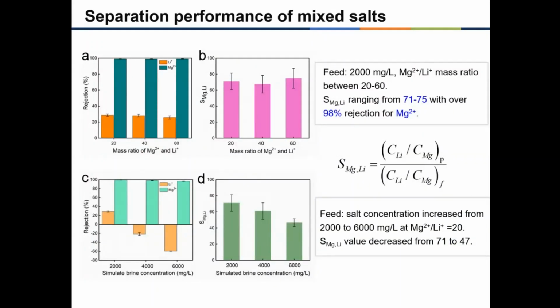We further tested the mixed salt of magnesium chloride and lithium chloride with total ion concentration of 2000 ppm, with the mass ratio of magnesium-lithium between 20 to 60. We found a high separation factor ranging from 71 to 75. The separation performance of the LBL membrane was strongly influenced by salt concentration. Figure C and D show that the separation factor decreased from 71 to 47 when the feed salt concentration increased from 2000 to 6000 ppm.